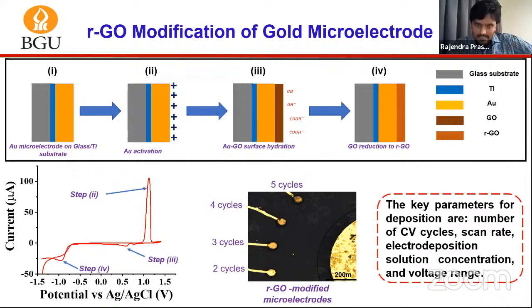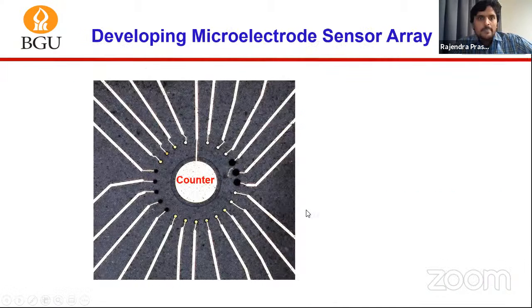So here you can see in the picture the modified microelectrode with different numbers of cycles. In cyclic voltammetry, we have two very important parameters, the number of cycles and the scan rate, how fast we do this process and how many cycles we use to modify them. As we increase the number of cycles, as you can see, the accumulation of the material is increasing. For 5 cycles, it looks more dark, so there is more material there.